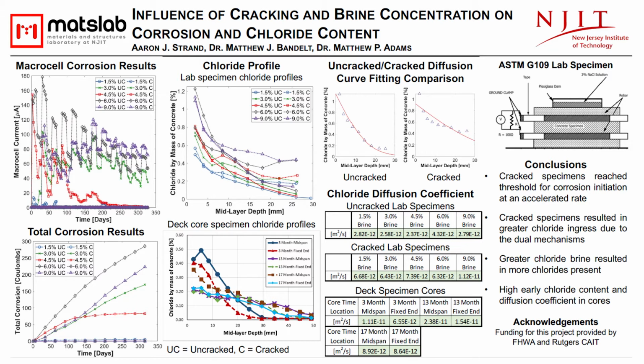The result of the specimen ponded at 6% reached the integrated current threshold faster than that of the higher concentration of 9%. This may be due to the fact that this specimen had the largest crack width of all tested specimens at 0.3 millimeters. The next largest crack width of a specimen was at 0.2 millimeters.